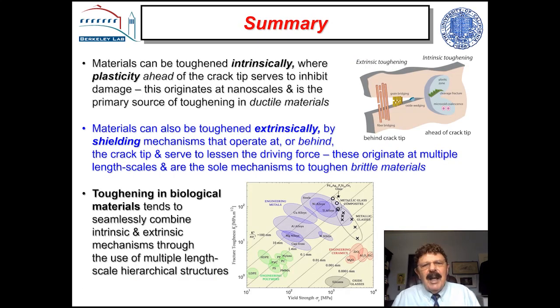Let me conclude by saying I've looked at how metals are toughened intrinsically, how ductile materials are toughened intrinsically. Brittle materials like ceramics are toughened extrinsically. The latter is associated with shielding behind the crack tip primarily, but the intrinsic ones are associated with plasticity ahead of the crack tip. But biological materials have this interesting function that they have multiple length scales. These different mechanisms are formed at different length scales, and so biological materials tend to be able to generate both intrinsic and extrinsic toughness, which gives them their remarkable properties.